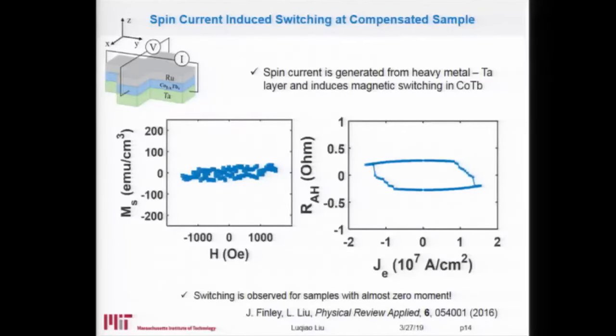So again, this is a magnetometry study where you see that the magnetic moment is almost 0. But at the same time, we apply a current inside this tantalum layer and utilize the spin Hall effect inside the tantalum layer to switch the orientation of this cobalt-terbium moment between those two opposite states. As you can see, by applying current, which is the x-axis, we can switch the anomalous Hall resistance from the high state to low state, or switch it backward by just simply flipping the current direction.